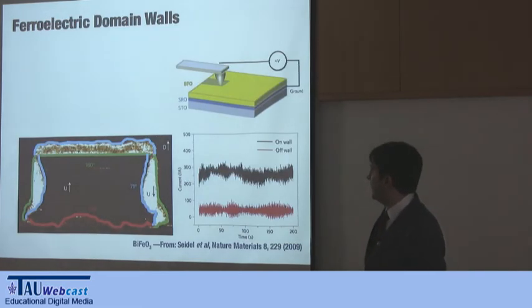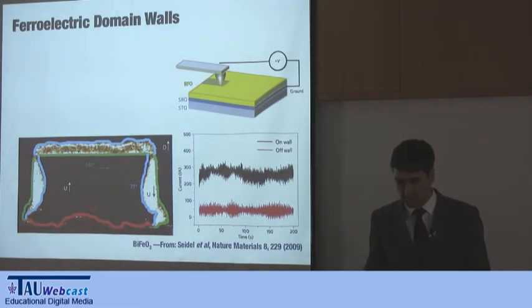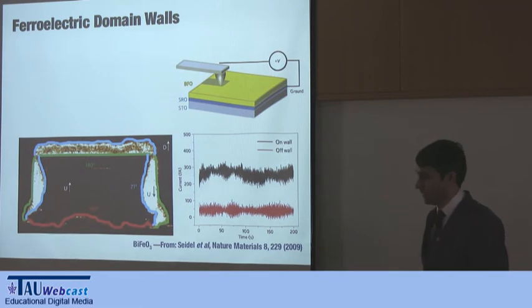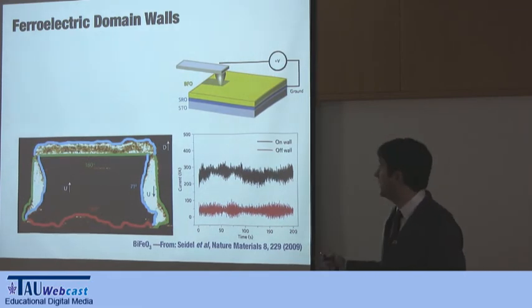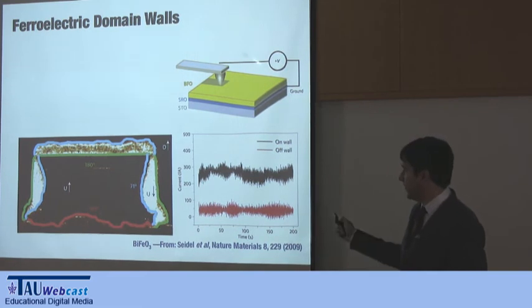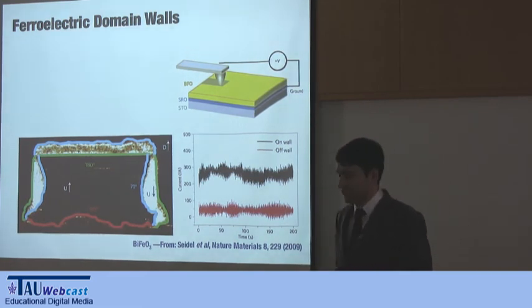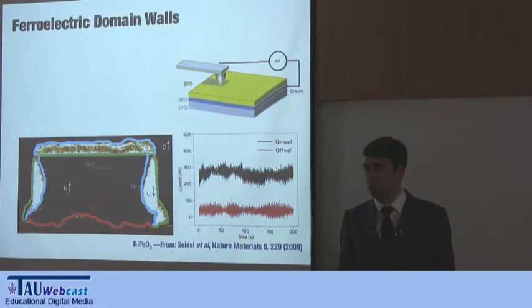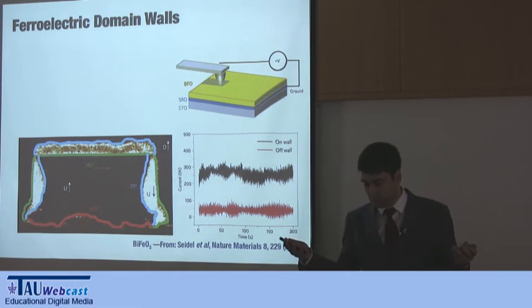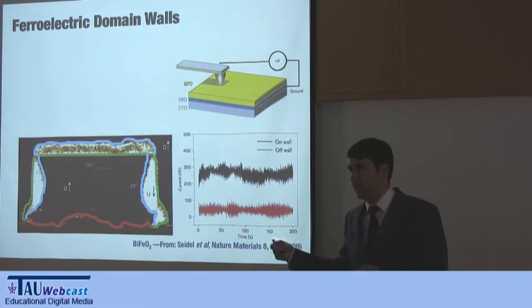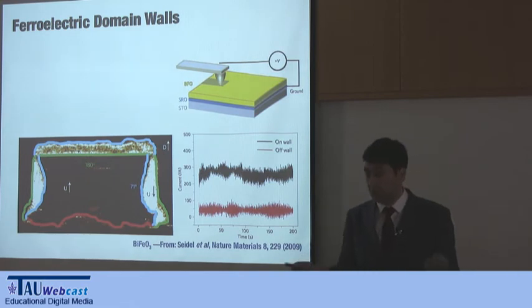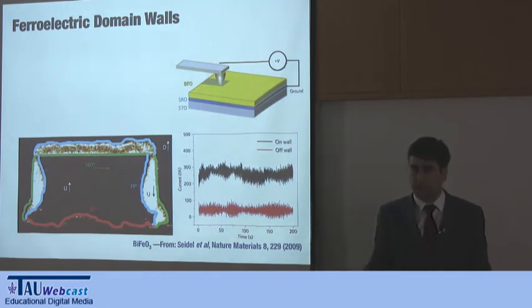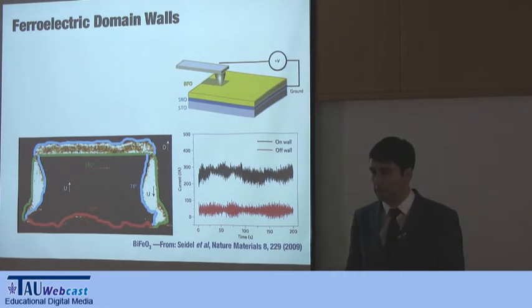I'm going to talk a bit, maybe fast, about the domain walls, just to show more complicated things you can study with DFT. The origin of this study is a paper in which they show that, well, ferroelectrics always show domain walls, right? If the ferroelectric was perfectly infinite, then all the atoms would want to move along the displacement patterns that I said, and that would be the ground state. But in real materials, you have a surface, and this would give rise to charges in the surface, and this would cost energy, so the system breaks into domains.